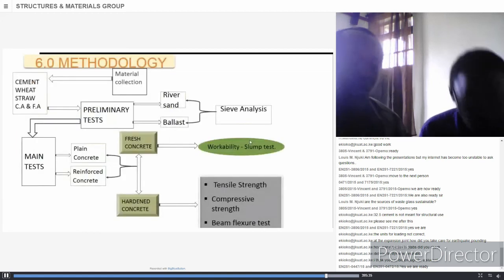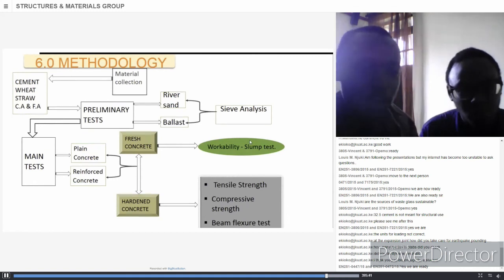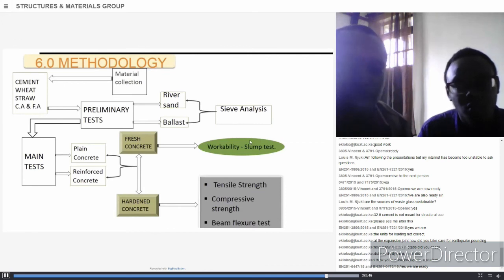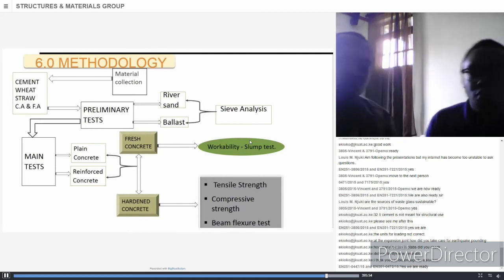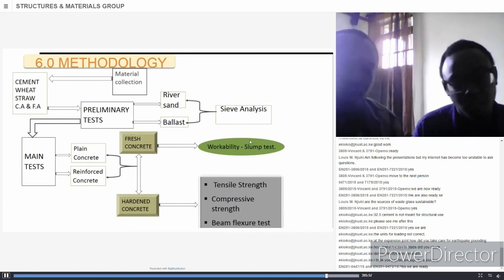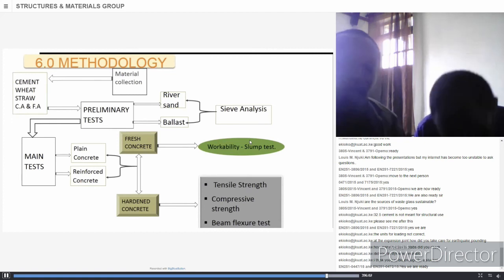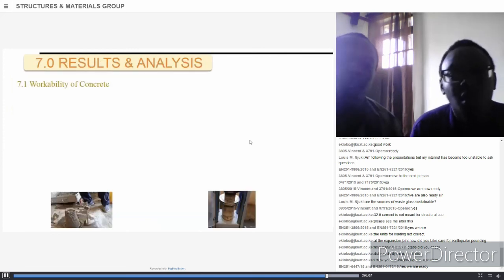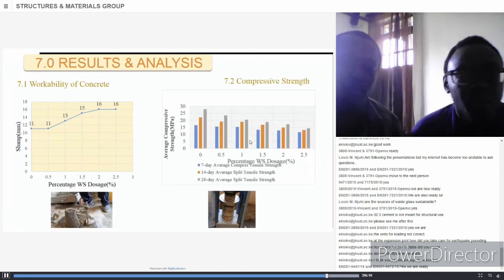For the methodology, we did a material collection where we collected fine aggregate, the wheat straw fiber itself, and the coarse aggregate. We did preliminary tests on the river sand and the coarse aggregate. We did sieve analysis first, then main tests on both plain and reinforced concrete. On the fresh concrete, we did a slump test, and on the hardened concrete, we did tensile, compressive, and beam flexure tests.